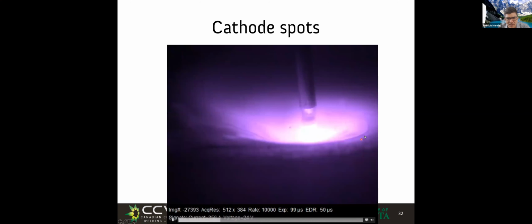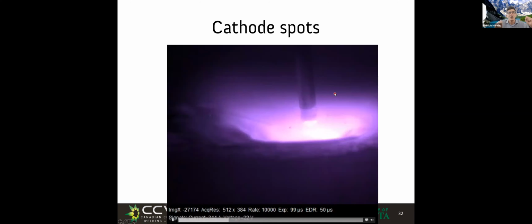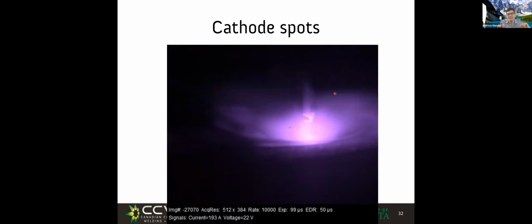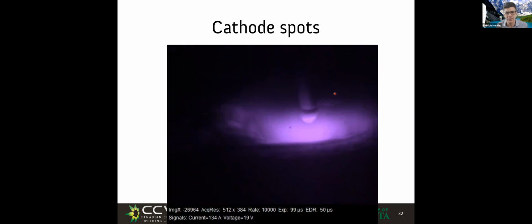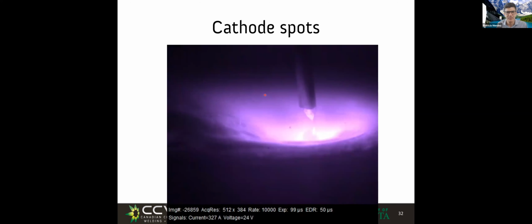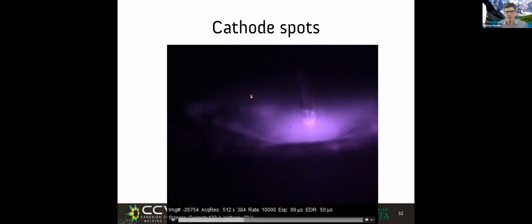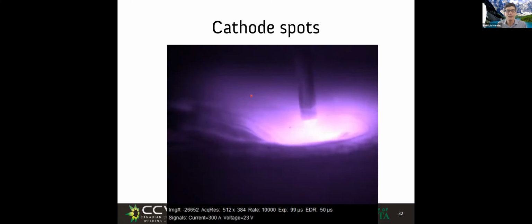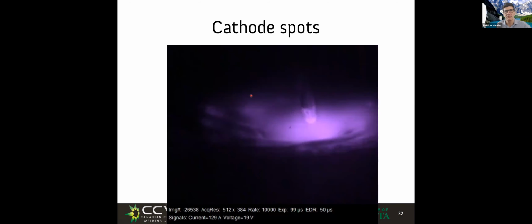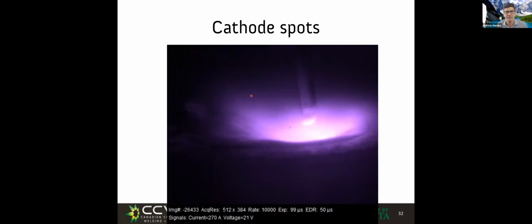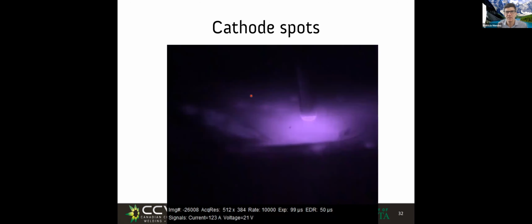You see that when the current is high, you see a shimmer in this image. And this shimmer, for example here at the edge of the arc, are the roots of all those lightnings that stay a little hotter, a little bit longer than the lightning. That's why we could catch it with our camera, right? This shimmer are the cathode spots in action. In this class, we're going to assume that the cathode is uniform, as if it had a constant current density, acknowledging that in reality, that constant current density is the consequence of an electric storm that is so intense that we stop seeing the lightnings and we see just uniform.